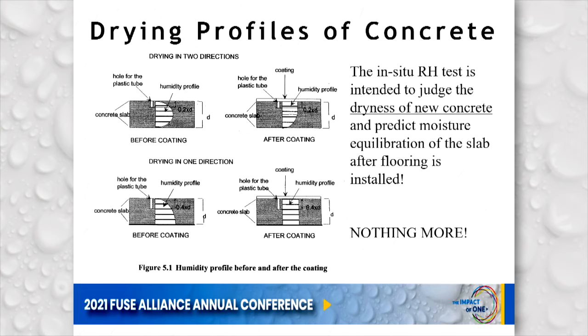Okay, the test itself comes to us from Europe. It was studied at Lund University, and the intent of the test is to judge the dryness of new concrete and predict moisture equilibration of the slab after flooring is installed. Nothing more. It was never intended for use on concrete that's been re-wetted somehow, whether it's topical or bottom, never intended really for use on concrete that has no vapor retarder.